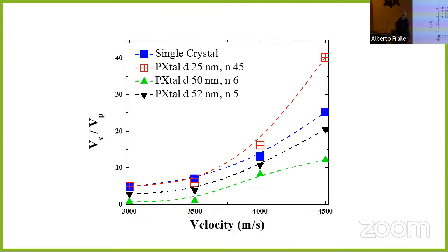Okay. I didn't pay too much attention to the curve yet. But we don't know yet if this is really the case or can change if we do more simulations. It probably won't change that much if we repeat simulations, because the crystals are big enough. I was thinking the reason could be that part of the energy is imparted in moving these nanocrystals a little bit instead of making the crater. So there can be a change of trend or a threshold, and then when you have a lot of nanocrystals, you are like a polycrystal. It gets a mess, so then it's even worse. You have a bigger crater for these high velocities.